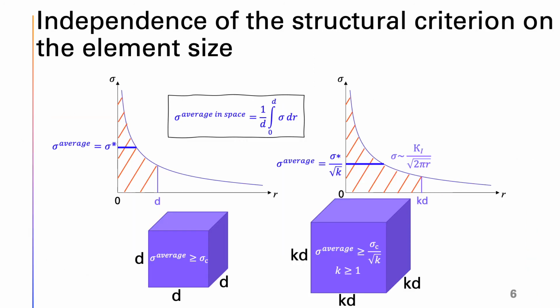Due to the heterogeneity of the stress field at the crack tip, the average stress value on a structural block strongly depends on its size. In case of the inverse root asymptotic approximation of the stress field, it's easy to find out that the average stress on a structural element of the size k times d is square root of k times less than on the structural block of size d. Consequently, the critical value of the average stress on a structural block of size k times d as well must be square root of k times less.